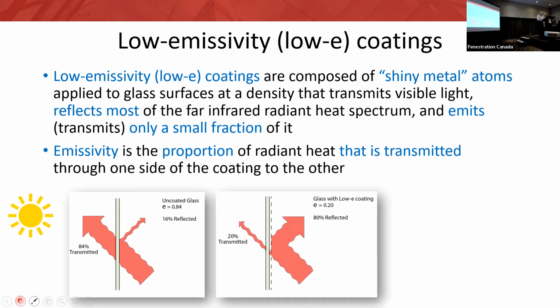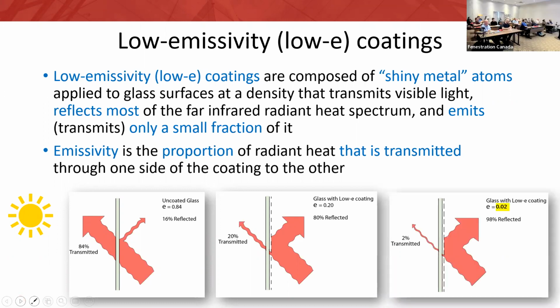If we take one of the earlier generations of low-E coating with an emissivity of 0.2, we would have a coating that reflects 80% of the heat back into the room, still transmitting, or emitting, about 20%. And if we look at probably the best low-E coating, the lowest emissivity coating we have in the residential window sector, which would be a triple silver type coating, your emissivity is 0.02, which means only 2% of that radiant heat energy is transmitted through that coating. 98% is reflected back into the room. So what we really have in low-E coatings are highly effective reflective coatings that are essentially invisible, but doing a lot to keep the heat in our buildings.